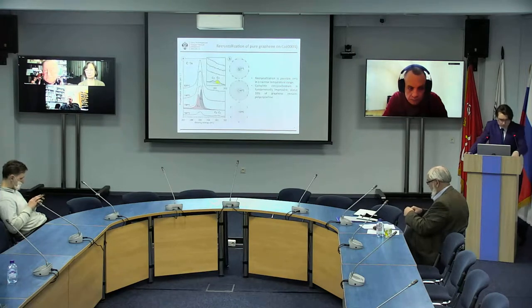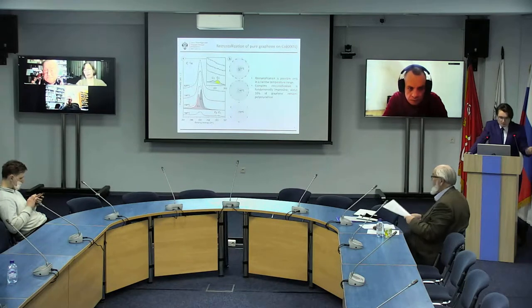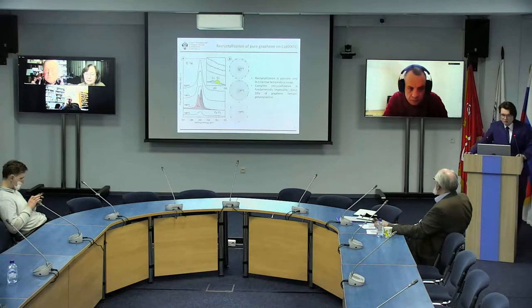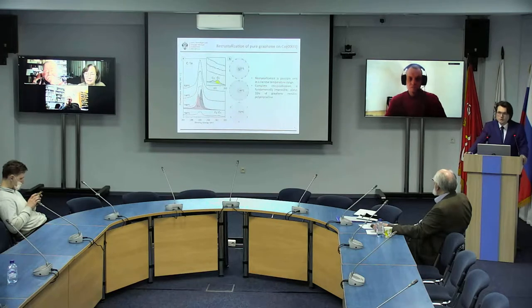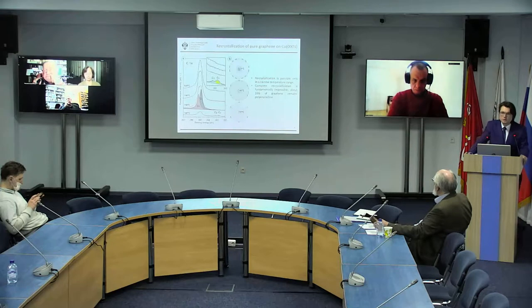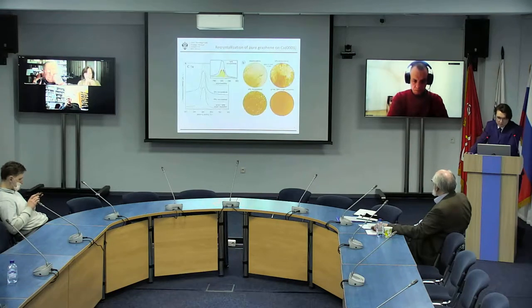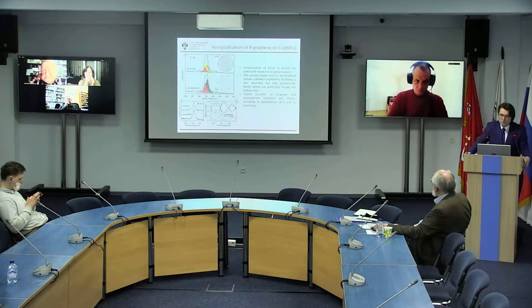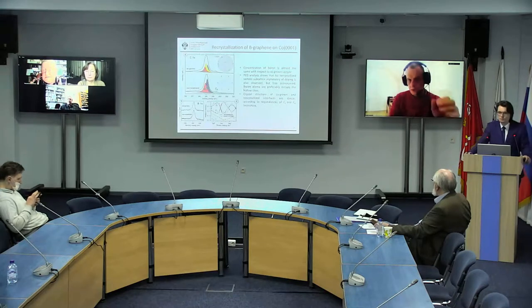And as for Fourier, it is used mostly in cases when we measure two-dimensional diffraction images. In this case, we measured a set of spectra and used expansion to assess the change of intensities of these components. And then we carried out the theoretical processing that allowed us to correspond this type of diffraction dependency to a specific structure. And this is also observed in case of boron-doped graphene, and in case of pure graphene, and in a number of other structures that were measured later on, not as part of this thesis. So we just continue the use of this data in our lab.